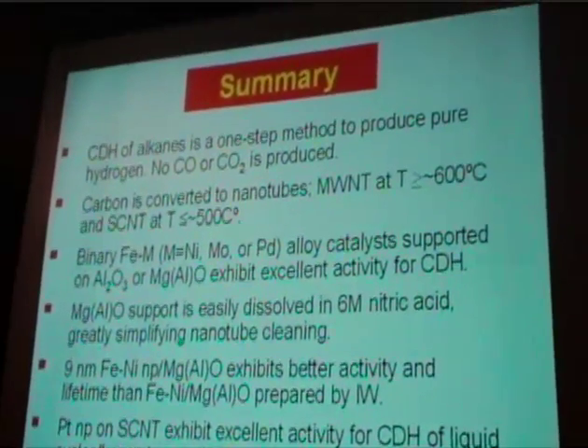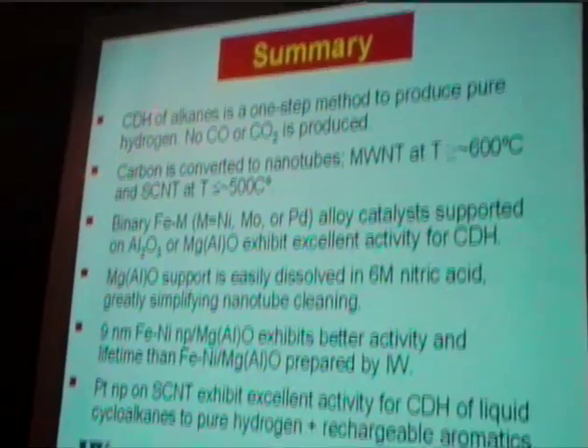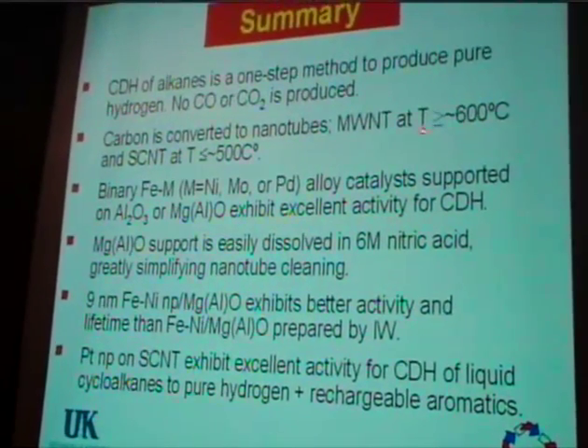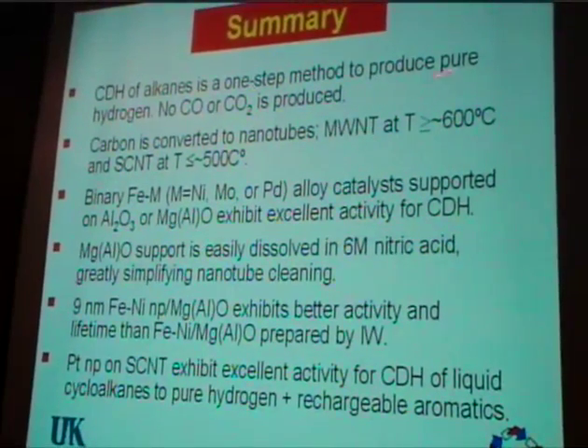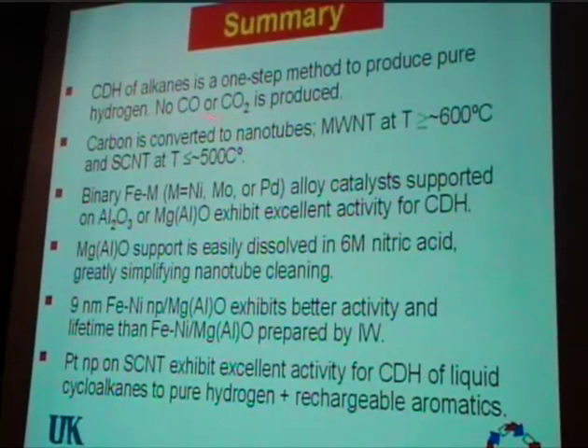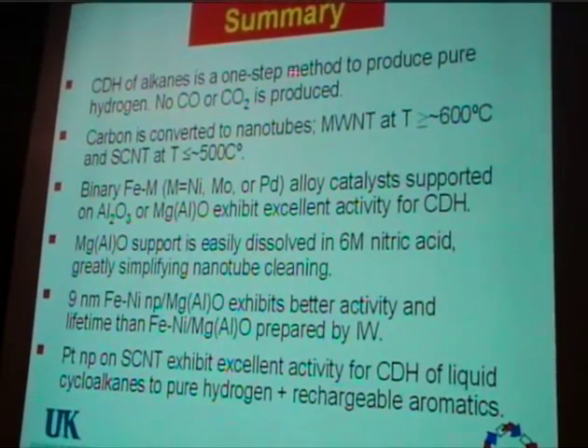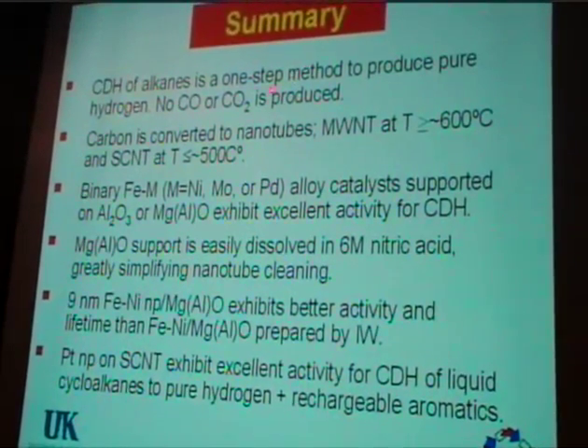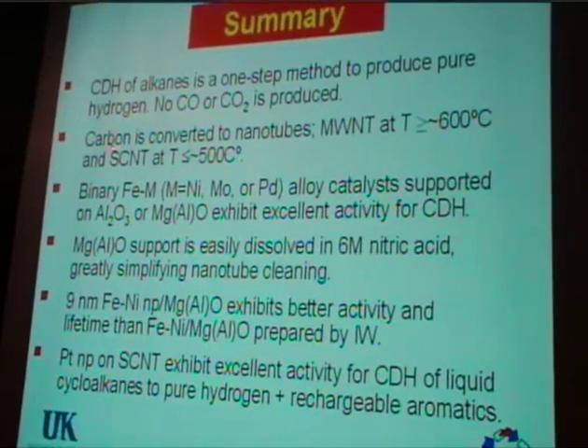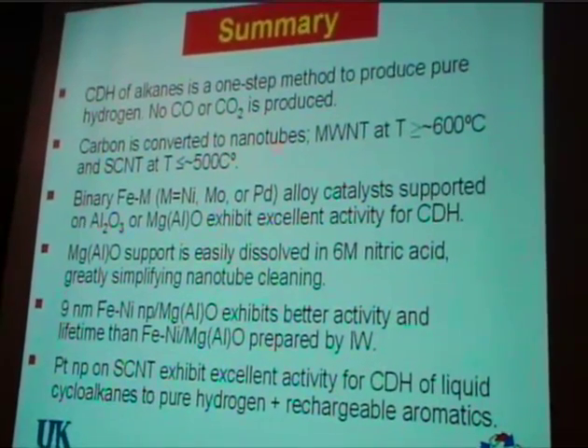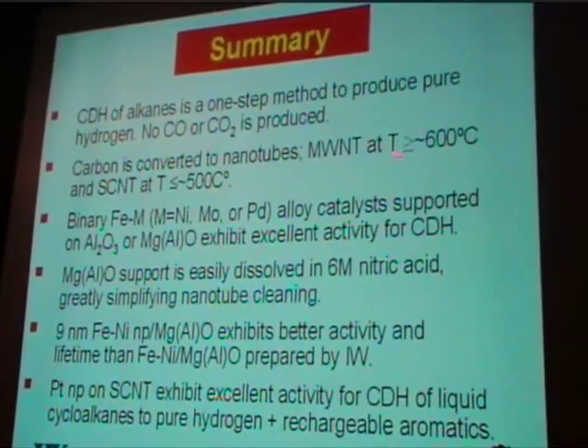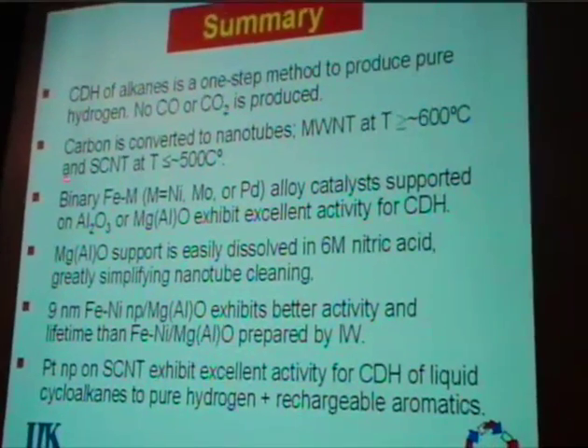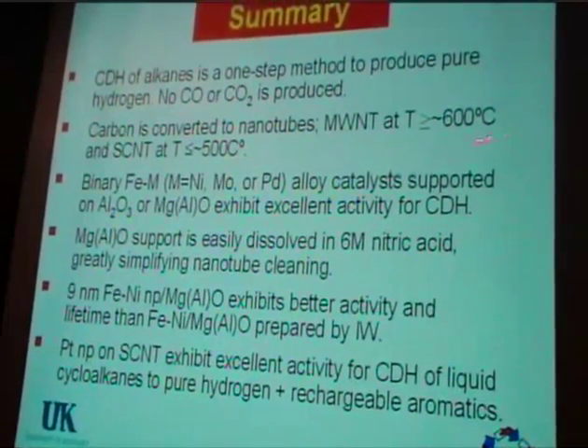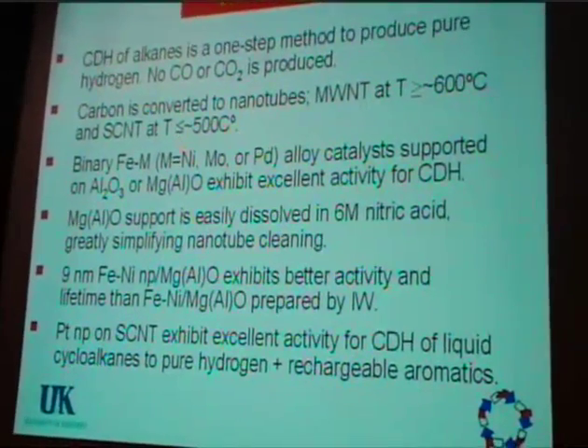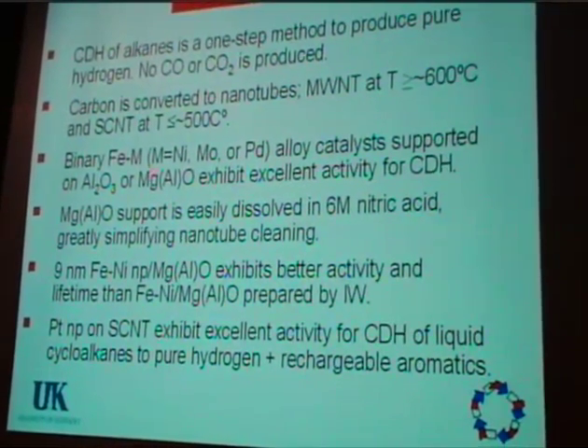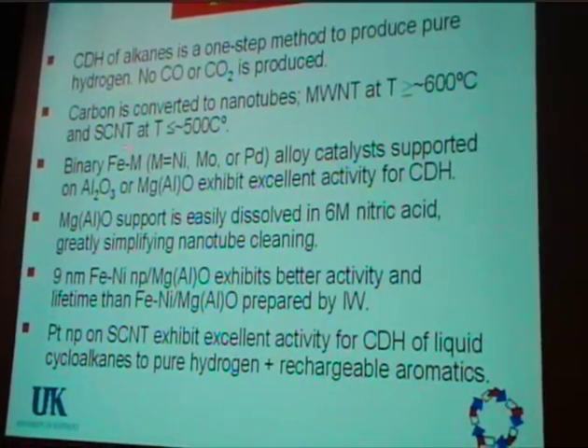So, to summarize, catalytic dehydrogenation of alkanes is a one-step method to produce pure hydrogen with no CO to poison your fuel cell catalyst or no CO2 to produce global warming. Carbon is converted to nanotubes. You can control the form of the nanotubes by varying the temperature of the dehydrogenation reaction. And the catalysts are very cheap.